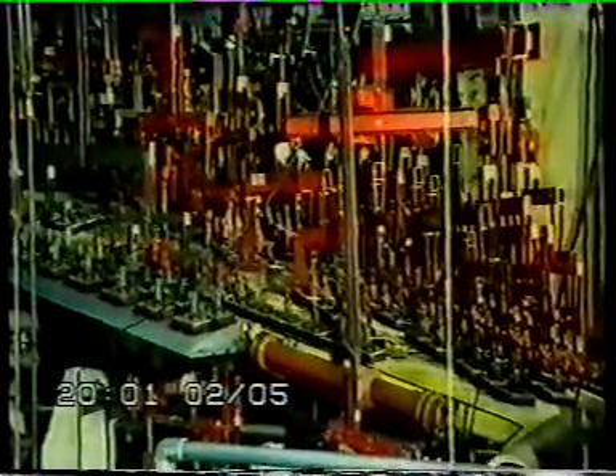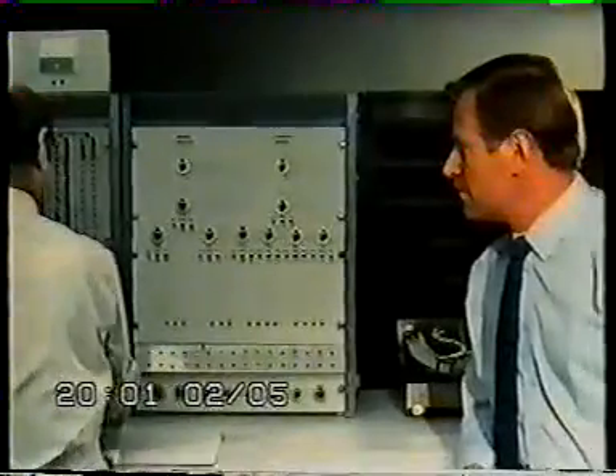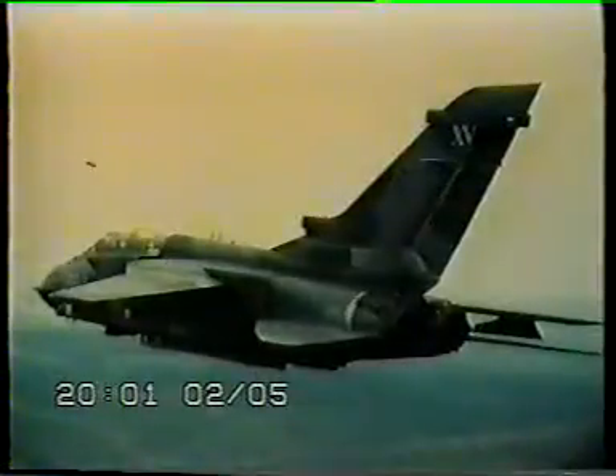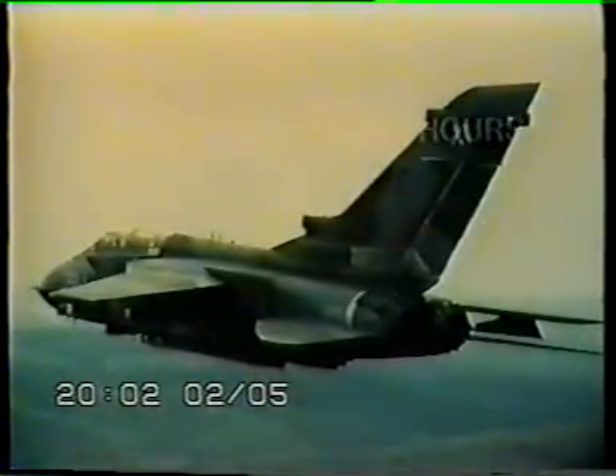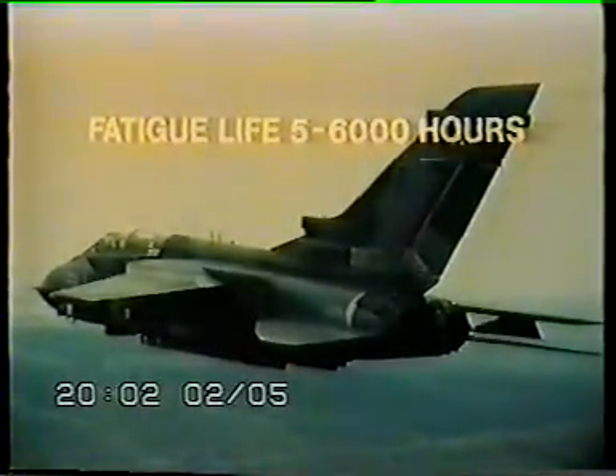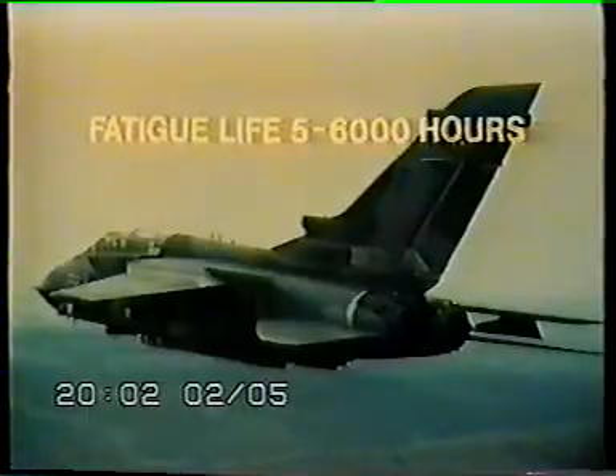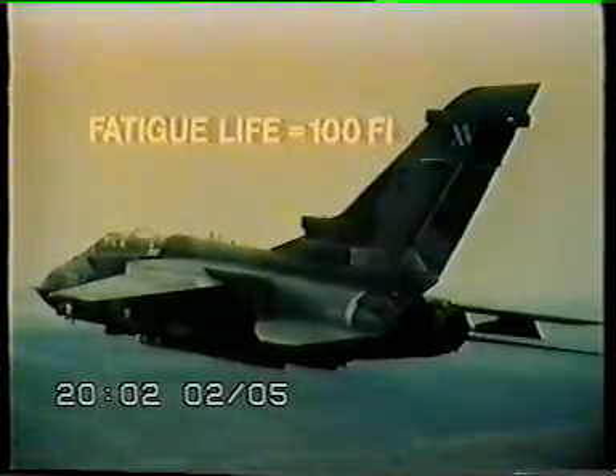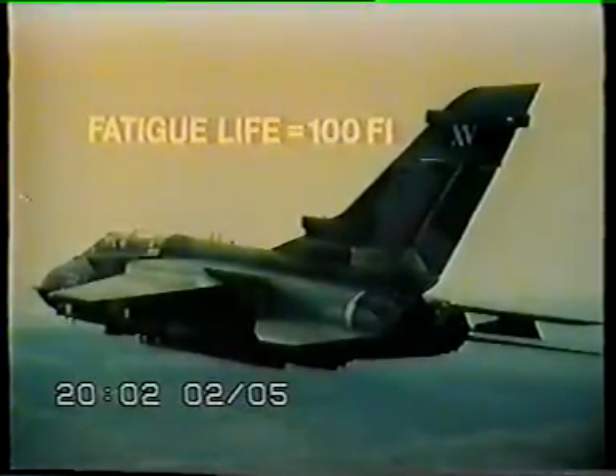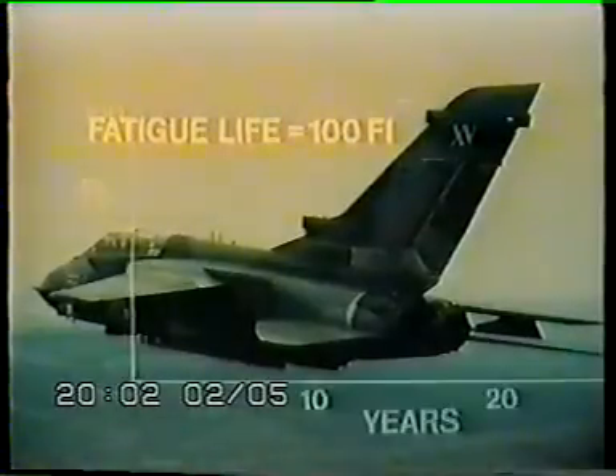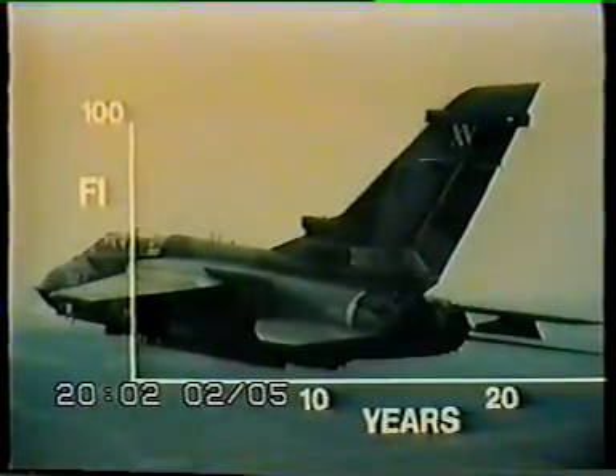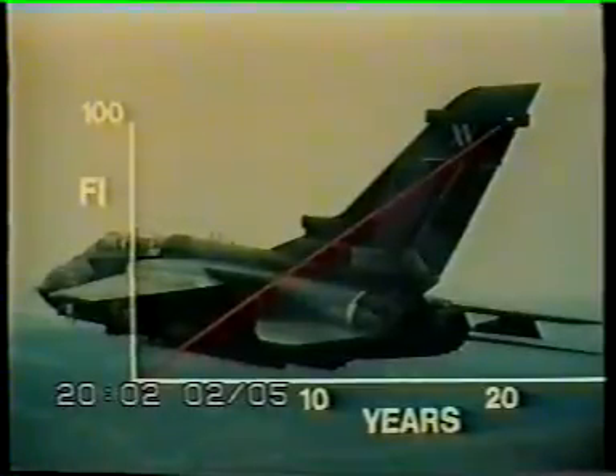Based on all this testing and data, the designer calculates a value for what is known as the mean life of the aircraft. By applying certain safety factors to allow for any scatter in the results, we obtain a safe life, known as the fatigue life. For modern combat aircraft, a planned fatigue life of 5,000 to 6,000 hours is fairly typical. The damage expected during this life is now made equal to a number of fatigue index units, FIs, ideally 100. This is done because the number of load applications can't be related to flying hours. So, if the aircraft is to have a life of 20 years, it can use up an average of 5 FI each year. If it uses more, the aircraft won't last for its intended life.